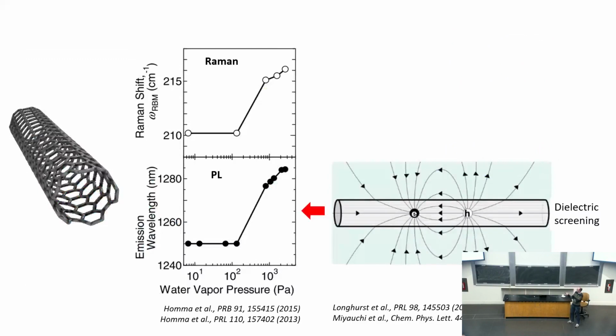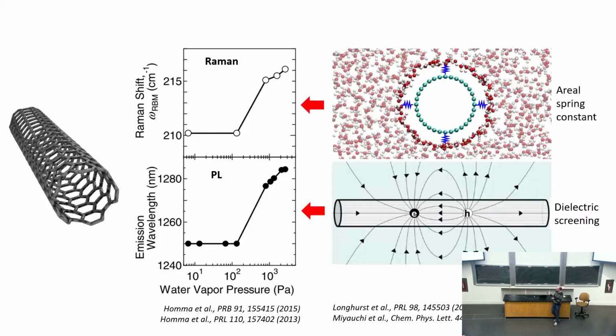Just going to show here the two tools that have been used in these studies, photoluminescence and Raman spectroscopy. Photoluminescence looks at the optical transition energy. That's actually an excitonic transition. When you increase water vapor pressure, water will accumulate on the outside of a CNT, similar to the inside. But in this particular study, it was on the outside. What happens is your dielectric screening changes, so your exciton has a different energy depending on the presence or absence of exterior water.